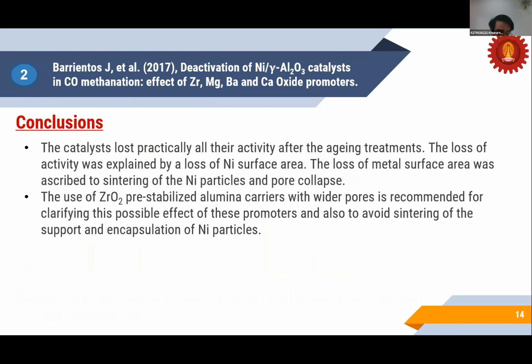Conclusion: the catalyst lost practically all its activity after the aging treatment. The loss of activity was explained by a loss of nickel surface area. 2 minutes left. The loss of metal surface area was ascribed to sintering of the nickel particles and pore collapse. The use of a zirconium oxide pre-stabilized alumina carrier with wider pores is recommended for clarifying the possible effects of this promoter and also to avoid sintering of the support and encapsulation of nickel particles.